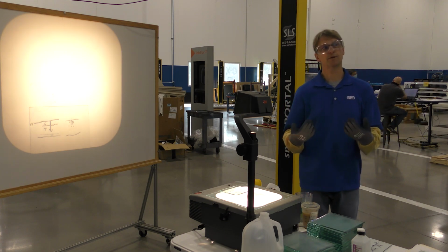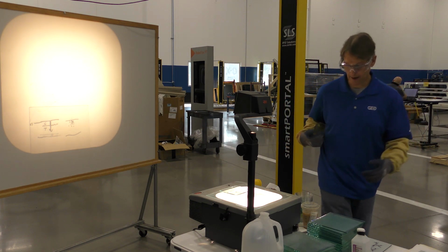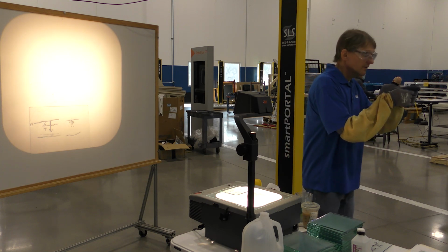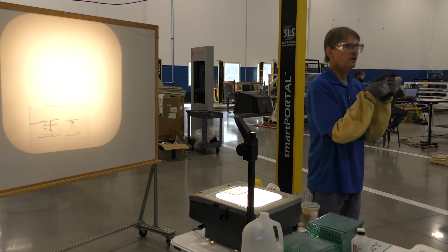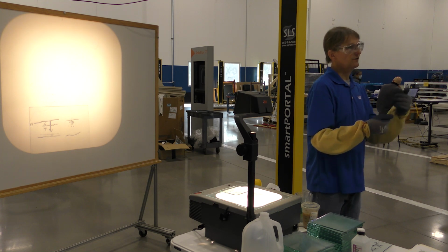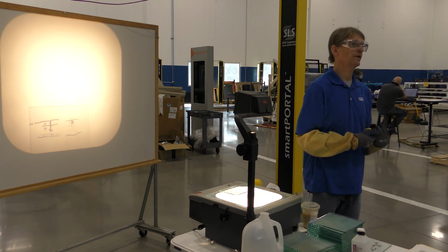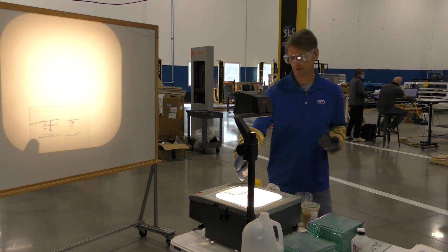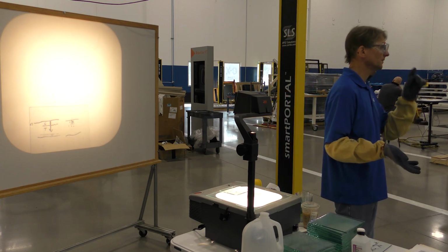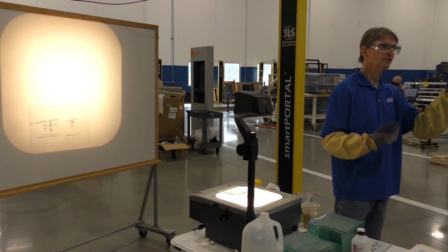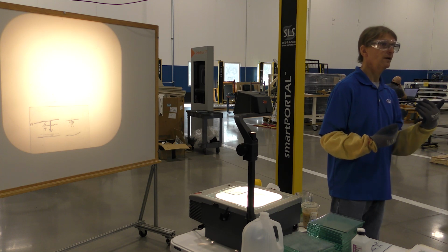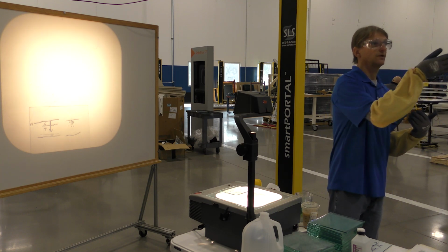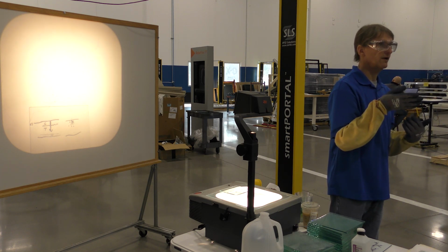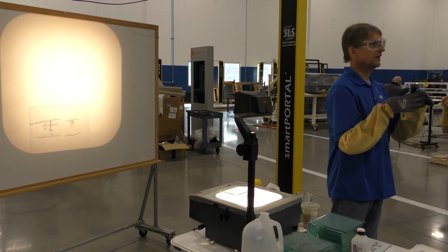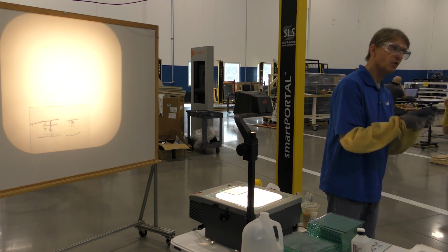Kind of the same thing happens with glass, where in order to break a score line, you have to drive beyond the compressive layer into the tension layer of the glass. So there's internal stress within the glass. That's why we need to go a certain depth in: if we don't break through the compressive layer, we're never going to get into the tension, and it won't be so easy to break.